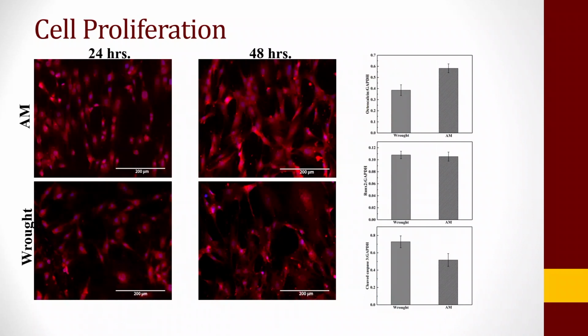So finally, as far as the cell proliferation experiments are concerned, again, these are the MC3T3 pre-osteoblast cell lines. So you could see that the cells are proliferating. When you compare 24 to 48 hours, you could clearly see that the cells are proliferating, and they seem happy in the sense that their lamellipodia or filopodia are expanding. And at the same time, if you compare the wrought and the additively manufactured, you could see that maybe the wrought is behaving a little bit better in the first 24 hours, but after 48 hours, you could clearly see that for additively manufactured, the cells are much more proliferating.